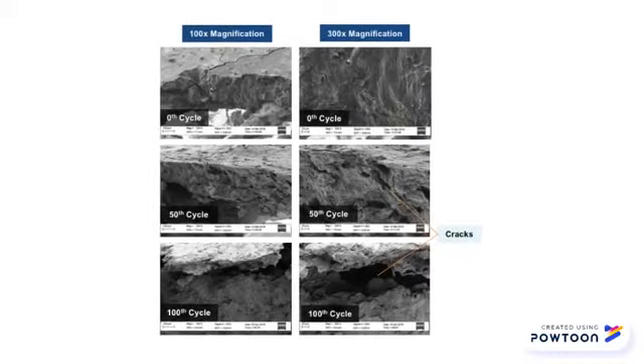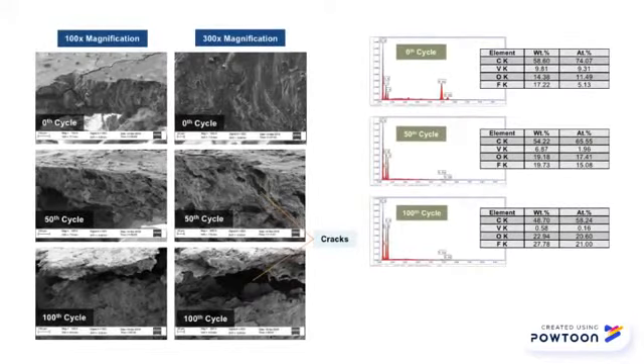The morphology of the LVO anode indicates that the agar binder plays a vital role in maintaining the cohesion of the LVO particles. After 50 cycles, we can see some cracks occur. A moderate contact loss and active metal deterioration might lead to an efficiency decay of the electrode. But the agar binder used to bind the LVO and graphene presented a significant result in this study. The result can be proved by the EDX result also.